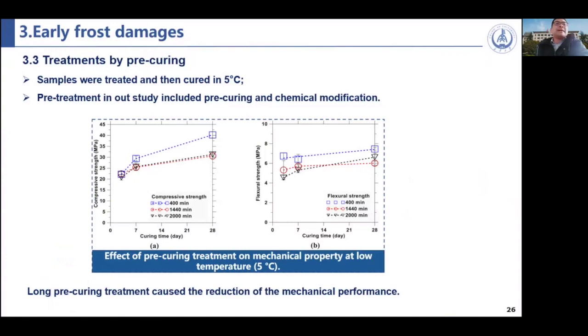And then we want to find some treatments against the early frost damages, or to improve the performance at the early ages. So we use two methods. First one, we treat the sample by pre-curing. We put the sample under the standard curing condition, and then cure it at 5 degrees. This is lower than the standard condition. The pre-treatments in our study include pre-curing and chemical modification.